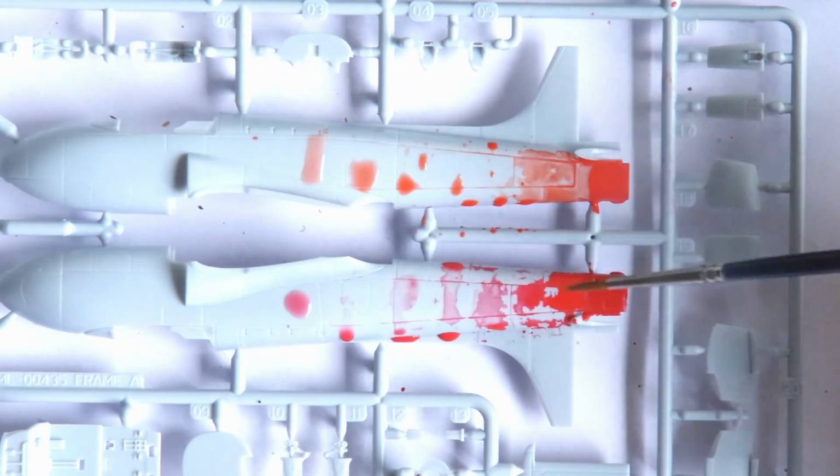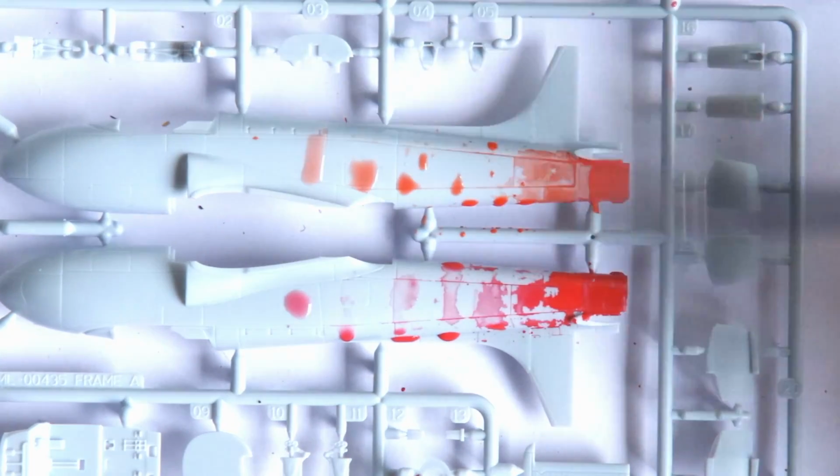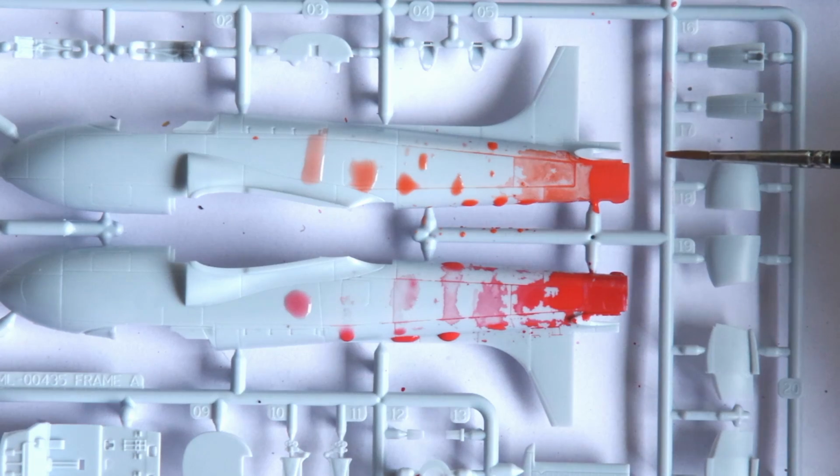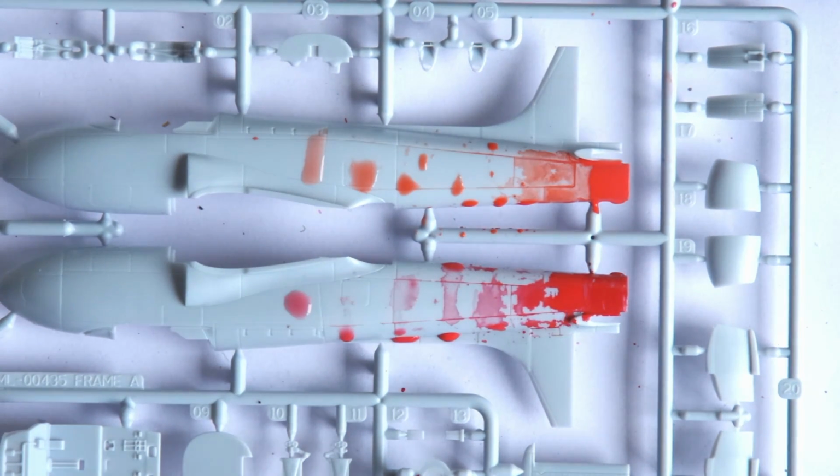You can see in both cases the paint is covering the plastic, and as it is diluted, its ability to wet the plastic surface is overcome by the surface tension of the water. I think the Tamiya paint does a better job initially, probably because even 10% solvent is helping, but then it does seem to reach a critical threshold.